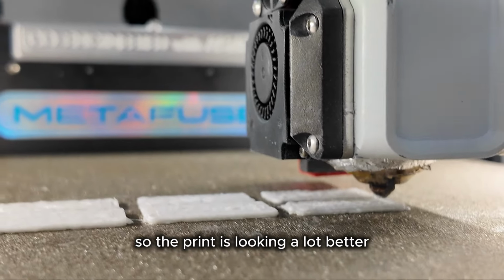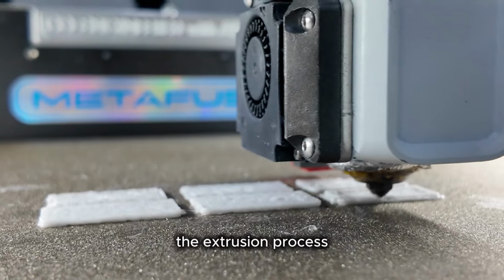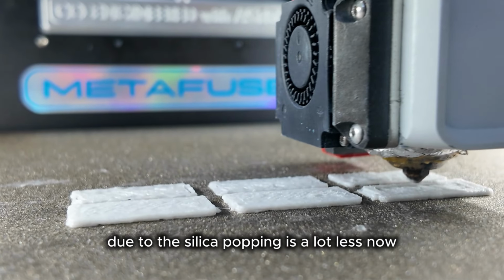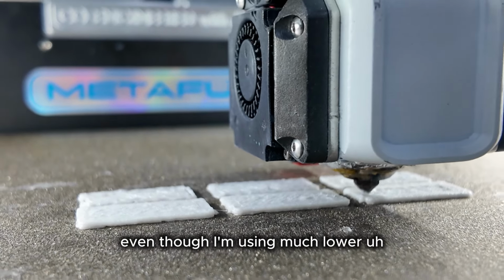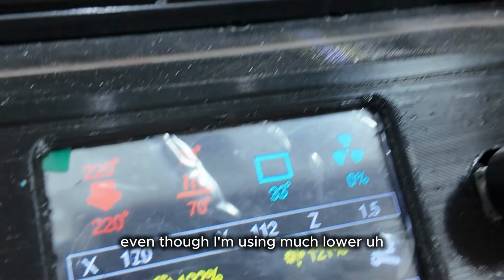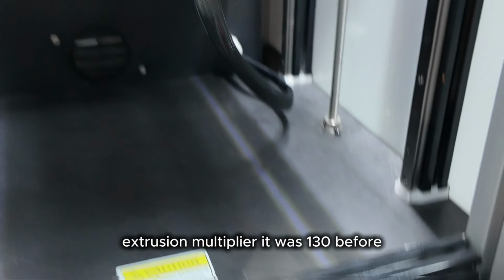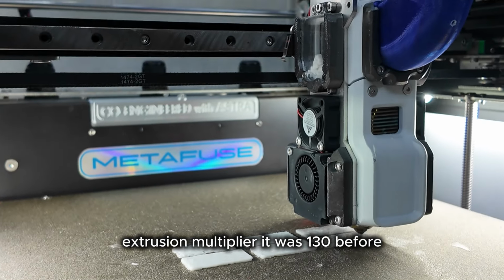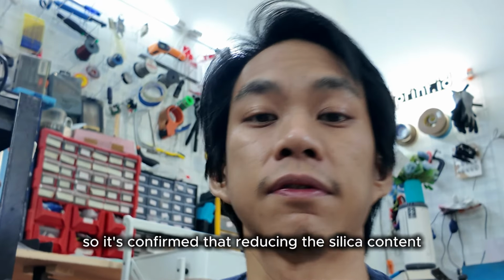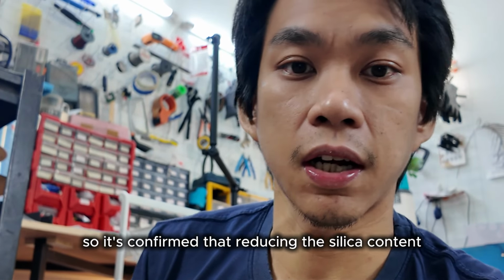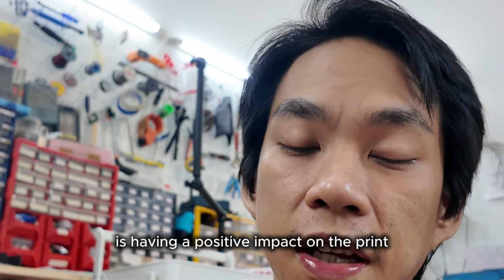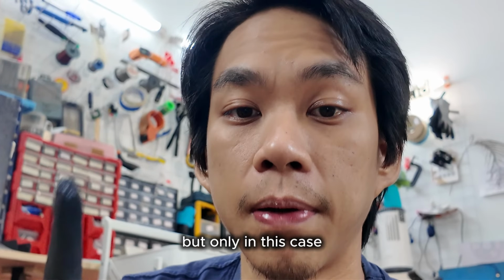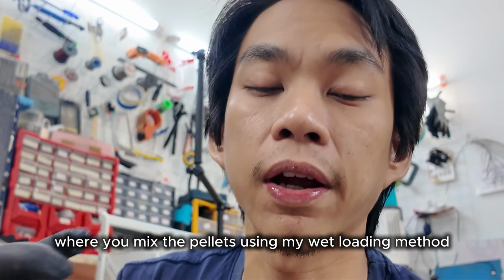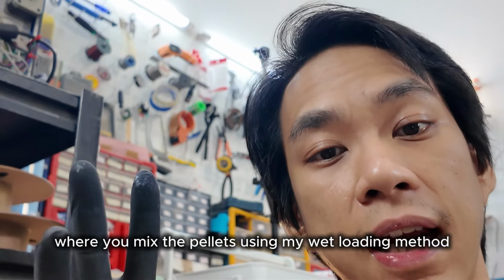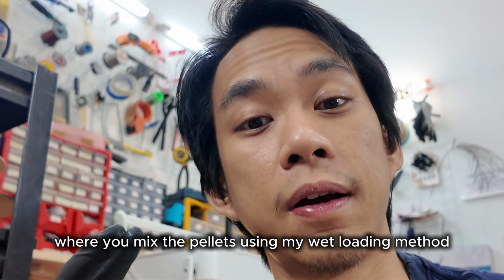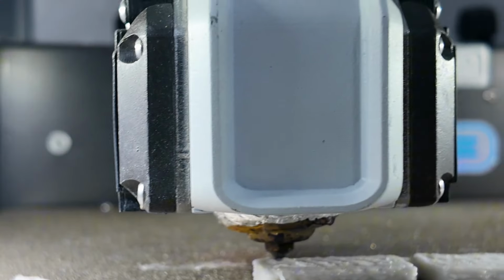So the print is looking a lot better. The extrusion popping due to the silica is a lot less now, even though I'm using a much lower extrusion multiplier. It was 130 before. So it's confirmed that reducing the silica content is having a positive impact on the print, but only in this case where you mix the pellets using my wet loading method.